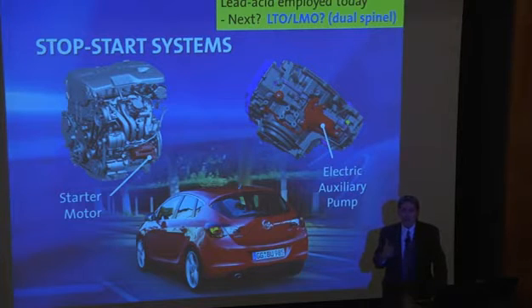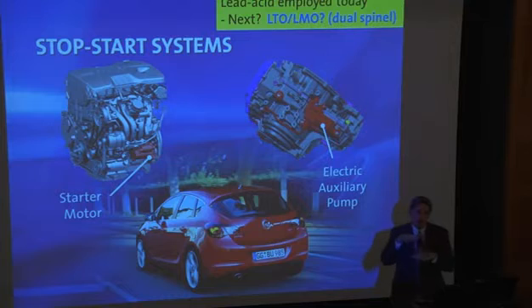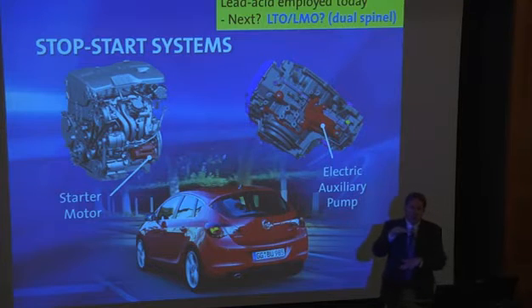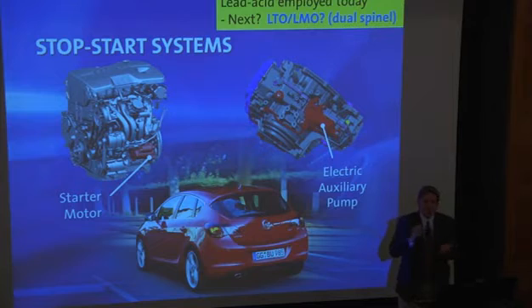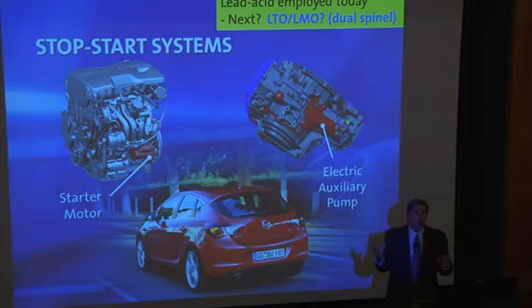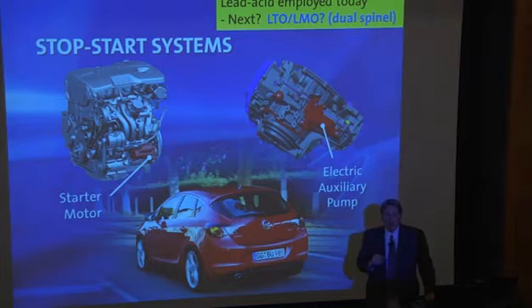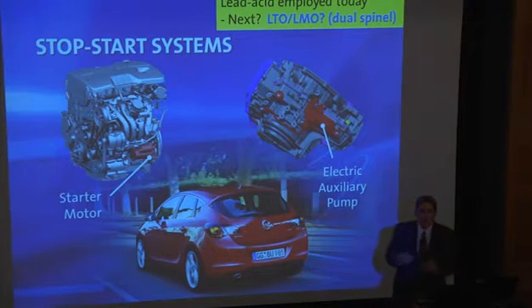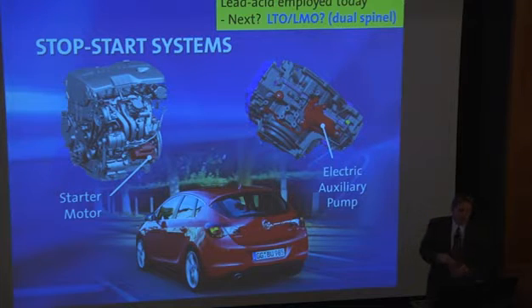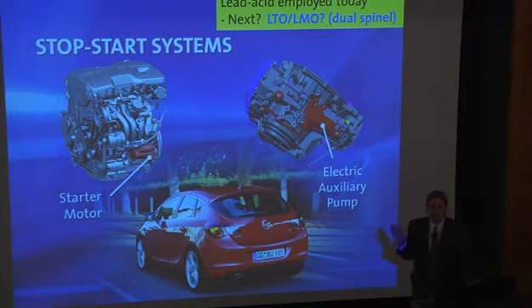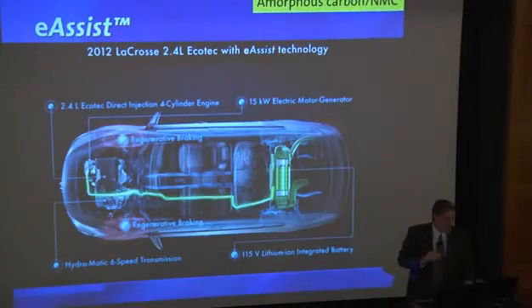My thought is if I was going to pick my favorite material, it would probably be an LTO, lithium titanate negative electrode. It's a so-called zero-strain material. So when you put lithium in and take it out, the host lattice hardly changes at all, hardly breathes. It's an open three-dimensional spinel structure, and lithium transports quickly in and out of the structure, giving very high rate operation. Arguably the best positive electrode that is fairly low cost would be lithium manganese oxide. It's also a three-dimensional spinel network. It is a very fast diffuser, so to speak, of lithium, and I could see where that could come on. Cost will be an issue, but I think these things will come to life for vehicle solutions, and the lithium dual spinel system will work out quite well there.